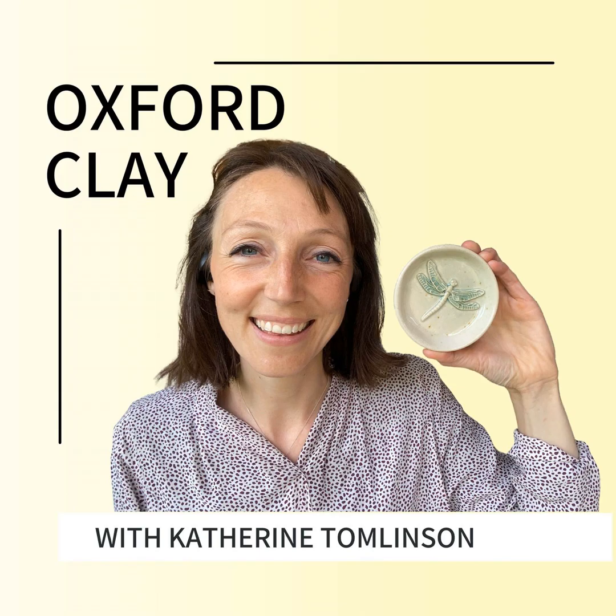So yeah, 350 grams of water. I actually think this glaze is ever so slightly on the thin side. I want it to be a bit thicker for when we do raw glazing, so we don't want to oversaturate the pot. So I think what we'll do is put it in the bottle, and then we can always pour off the top layer of water because all the glaze ingredients will settle. Then we can mix it up again and see how the consistency is then. It should be the consistency of single cream really for a glaze, and this is a little bit thinner than that. And for raw glazing we want it a teeny weeny bit thicker.